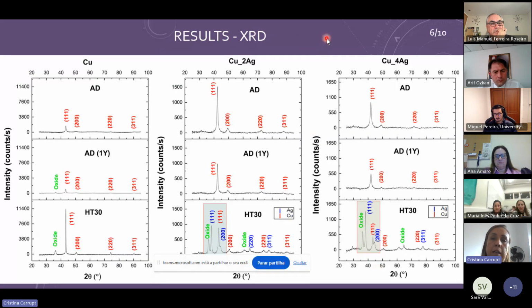The films were characterized regarding crystalline structure, and we can observe that in the as-deposition condition we can see the peaks of silver. After 1 year of aging, the peaks of silver are not visible. But after retreatment, this peak becomes visible. Maybe in this condition, because of the temperature of deposition, the silver is in amorphous form, or silver is coherent with the copper matrix. With the temperature of retreatment, the silver comes to a crystalline form and the peaks are visible.